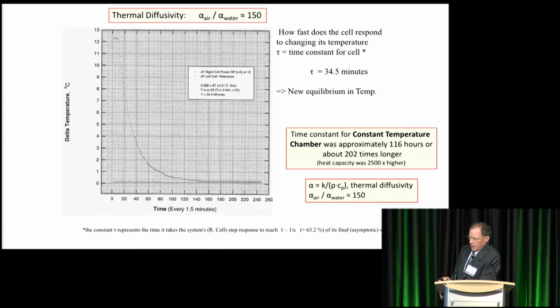However, the thermal diffusivity of air is 150 times that of water. So when the heat comes out of the cell, it rapidly diffuses into the media away, more so than water. And the only problem with using air is if there are any velocity currents in the air, they will spoil the situation. So that's why it was encased in a large chamber to exclude any thermal currents in the room.